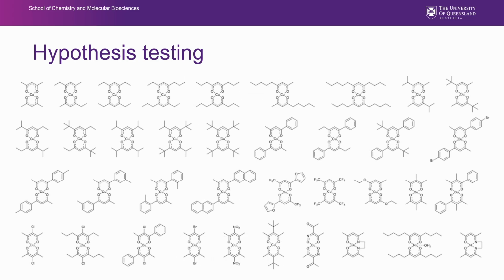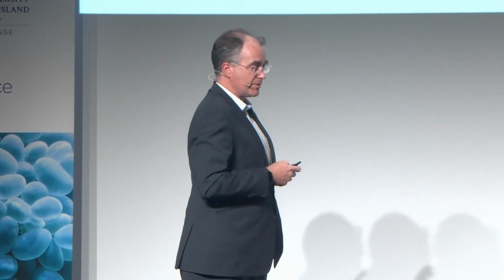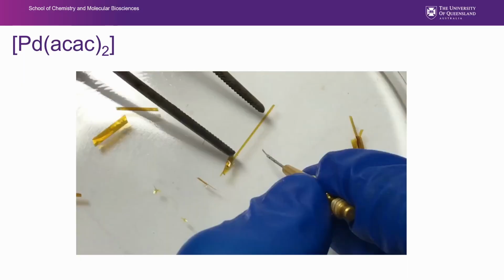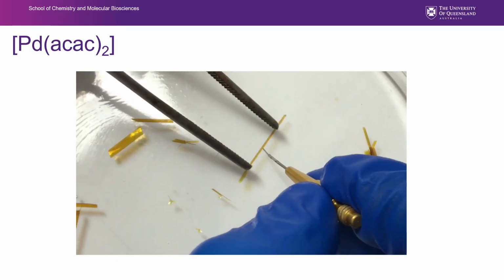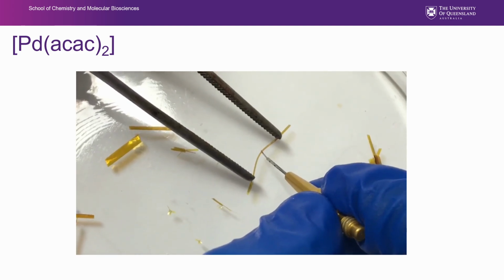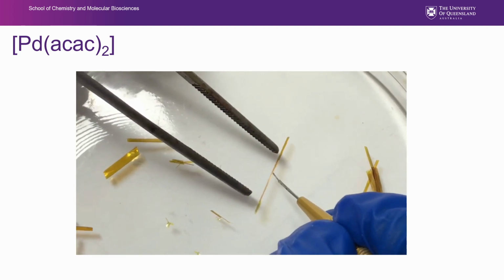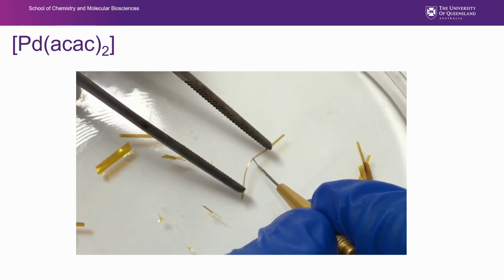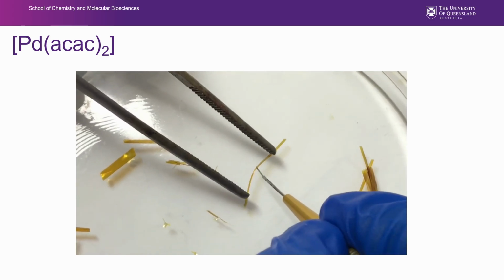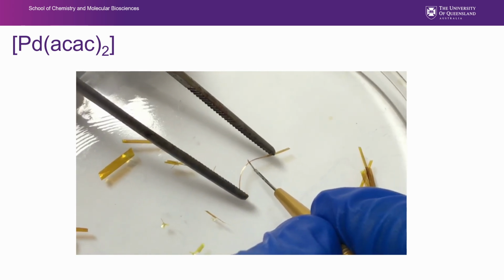And so these are the sorts of things that we went and made. So more than 100 examples now of very closely related molecules to work out how and why making individual changes will affect the elastic flexibility. Once we make these molecules, we grow them into crystals, and then we start to try to test them. And we don't test them in any particularly hard way. We simply try and do what's called a 3-point bending test on them. We just see if we can bend the crystal and if it straightens back out again afterwards.